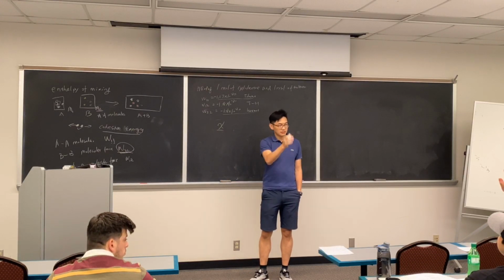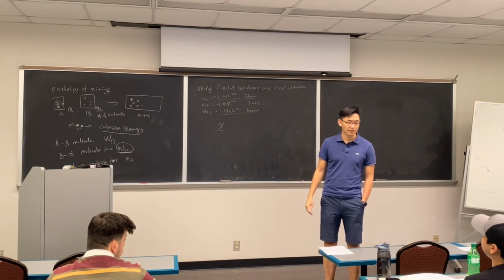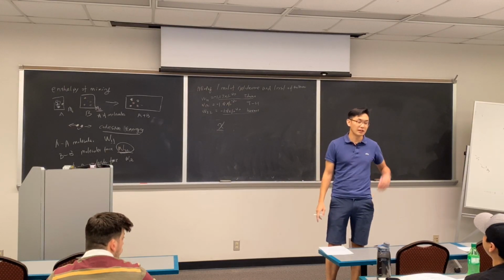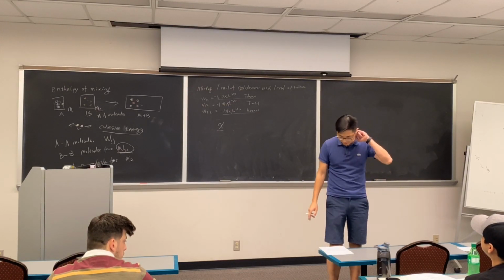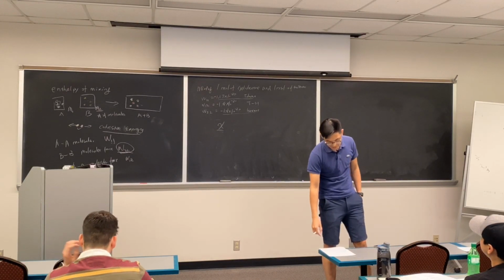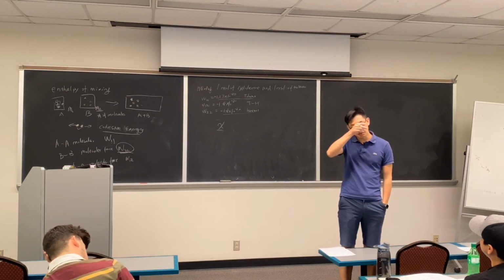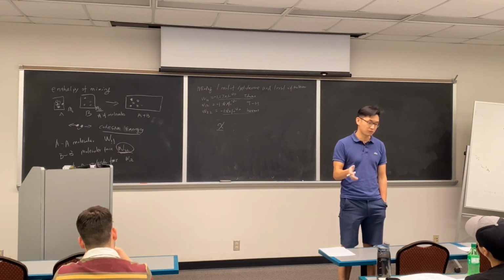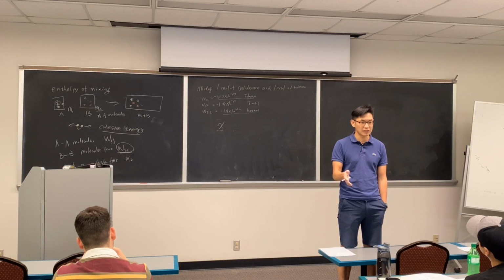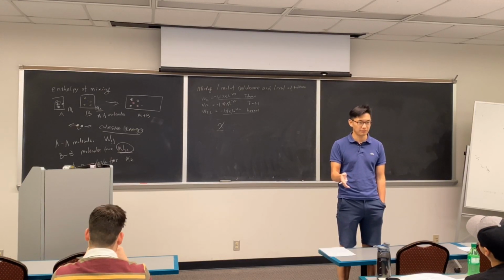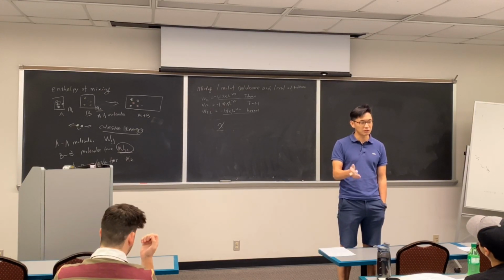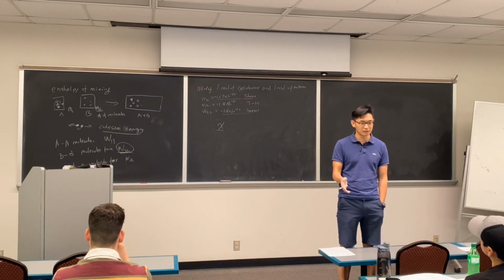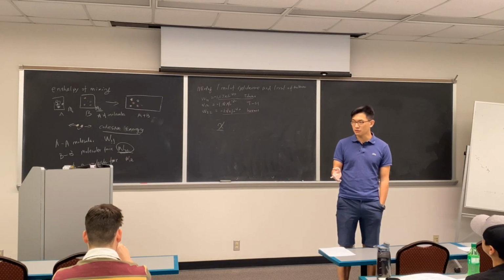How did they initially calculate chi? They measured it. They don't calculate. There are several ways people can measure chi. One classical way is using scattering measurements, and through some mathematical treatment, you can extract the chi for two given materials. You can build a database of known materials and their chi values. However, it doesn't work for unknown materials.